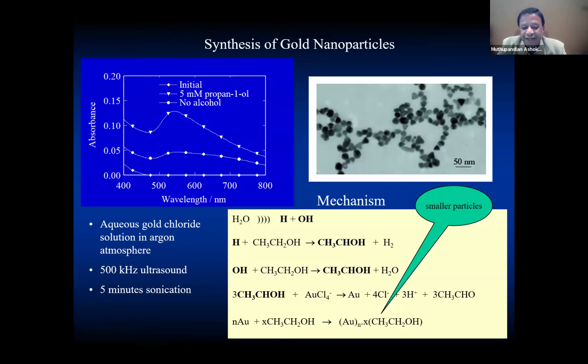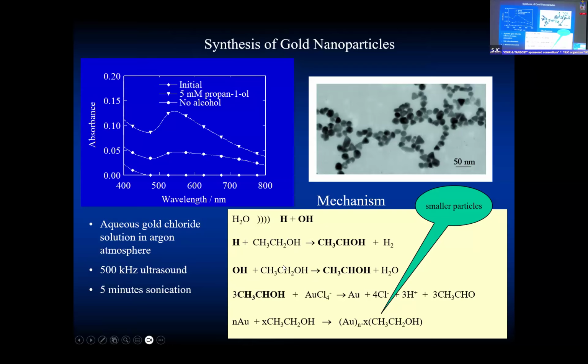So I can also increase the rate of the reaction by knowing some chemistry. For example, as I told you, hydroxyl radicals are oxidizing agents. Here we are doing a reduction reaction. We want to reduce the gold ions to gold zero by adding a small amount of organic solute like ethanol. I can convert the hydroxyl radical into an alcohol radical. This alkyl radical or alcohol radical is a secondary reducing agent.